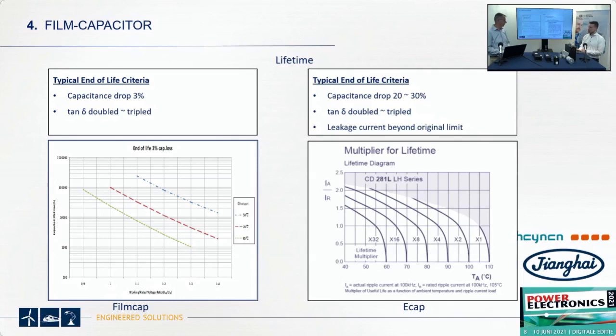Okay. And we start here with 70 degrees and 100,000 hours. This is the normal specified lifetime of film capacitors. And for ECAPs at 70 degrees, we have maybe the half lifetime. Okay. But at the end of the lifetime, a much higher capacitance loss. Okay. And this is the reason why you use film capacitors when you need a long-time stable component.